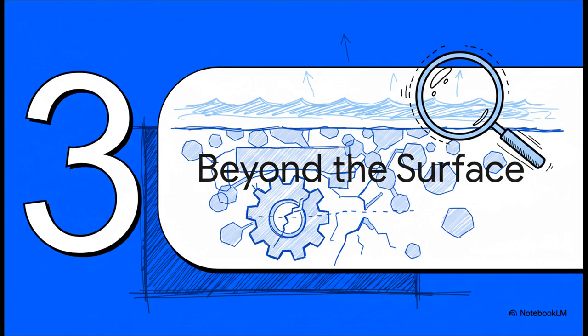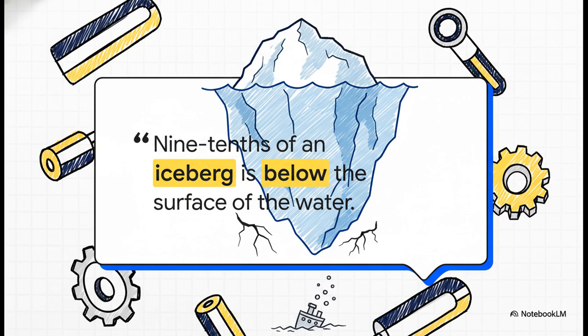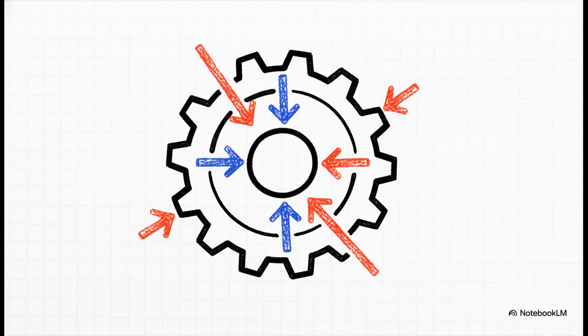To find the real culprit here, the real smoking gun, we have to look deeper, beyond what you can see right on the surface. And this iceberg analogy is just perfect. The hardness and the case depth that we can measure on the surface, that's just the tip of the iceberg. The real danger, the part that can sink the whole ship, is hidden from view. And that hidden factor, that massive part of the iceberg underwater, is something called residual stress. These are stresses that are literally locked into the material after it's made, even when it's just sitting on a shelf. It's like an invisible internal battle being fought inside the steel.